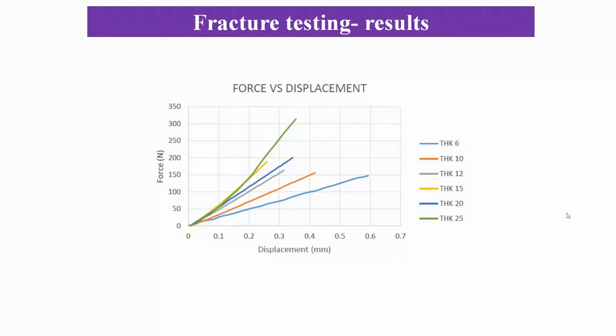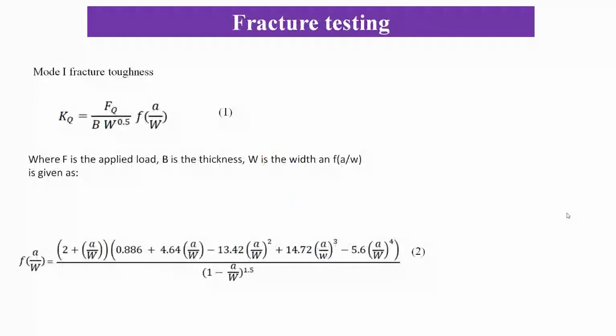The results of the SENB test, force versus cross-head displacement for different thicknesses of polyester specimens, are shown over here. Using the value of force and dimensions, as well as the geometry factor f of a over W, we can determine the value of fracture toughness using equation 1. The geometry function is shown over here in equation 2.